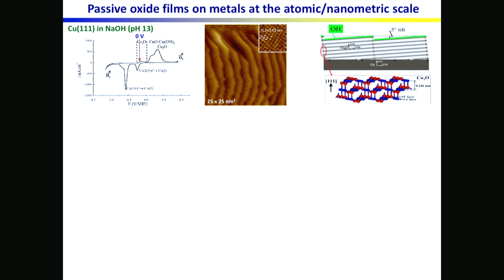And what you see are terraces and steps of copper oxide. As we started with a copper 111 very smooth surface with a degree of disorientation of less than 1 degree, you clearly see that the steps have a high frequency, so the terraces are not wide, and this means that something is taking place because we are starting from a very smooth surface. I will come back to that.